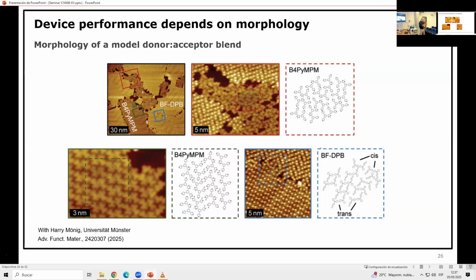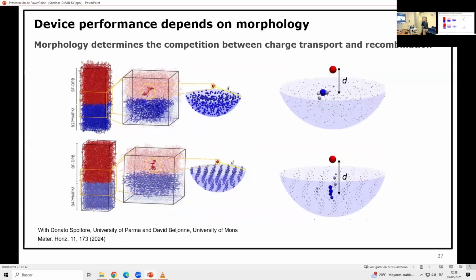So how important is it that you have these ordered regions? That's the nice thing. If you have this type of measurements with the STM, where you can see how the molecules arrange, you can put it in multi-scale models, where we work with the university in Mons, also in Belgium. The group of David Beljonne models them and makes these model interfaces. Here is an interface which would be very disordered, where all the molecules are a bit random. Then they calculate the size of the interfacial state, the one when the electron is just transferred. So they put the charge density on these molecules.